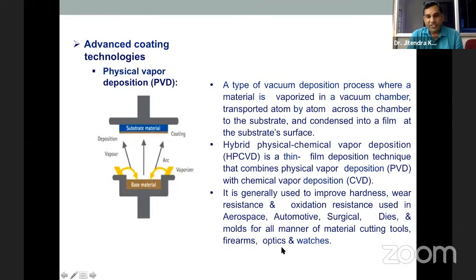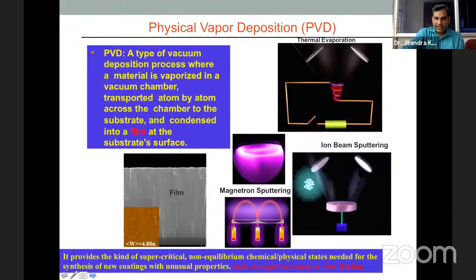You have seen your watches and your optics have a glass with scratch resistance. Why does this happen? Because of physical vapor deposition or chemical vapor deposition. According to the necessary actions, what type of coating and what the application is, we select the process. So this is the basic thing: how the plasma is generated, the material evaporates, and we coat it over as a film. And this film you can see by scanning atomic force microscopy, and by this you can see how the atoms are homogeneously dispersed over the complete surface.